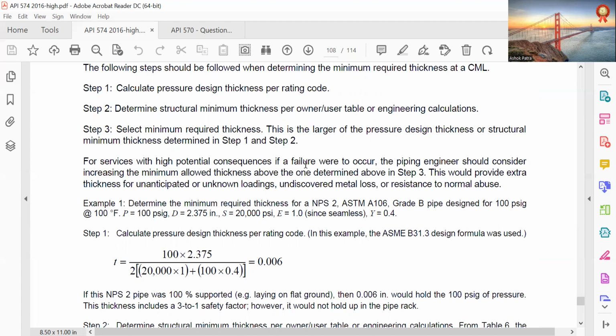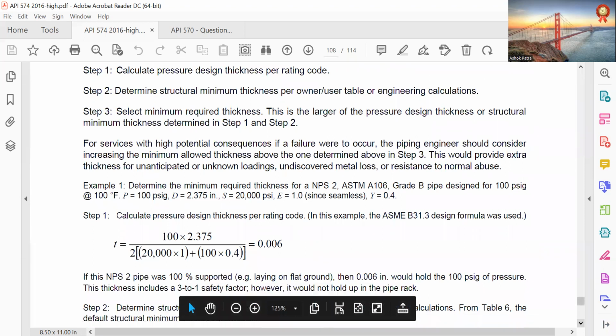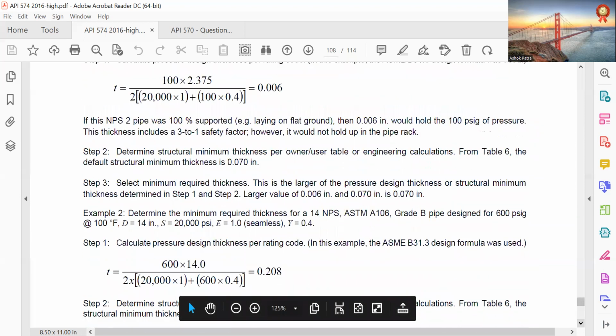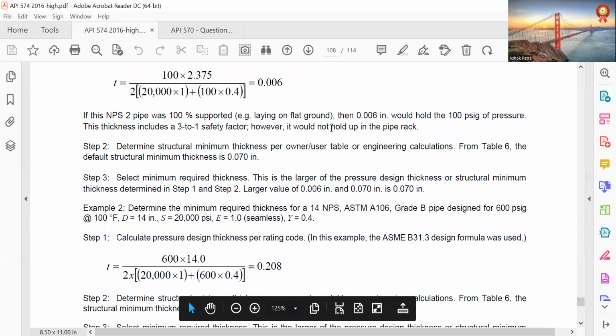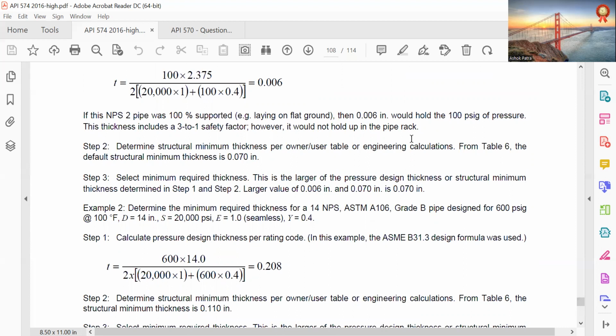Calculate the pressure design thickness for rating. So, determining the minimum required thickness of NPS 2 ASTM A106 Grade B, designed for 100 psi at 100 degrees Fahrenheit, with D equal to 2.375 inch, S equal to 20,000 psi, E equal to 1 since seamless, and Y equal to 0.4. They calculated t as 0.006. If the NPS 2 pipe is 100% supported, lying flat on the ground, then 0.006 inch would hold 100 psi of pressure. This thickness includes a 3 to 1 safety factor. However, it would not hold up in the pipe rack.